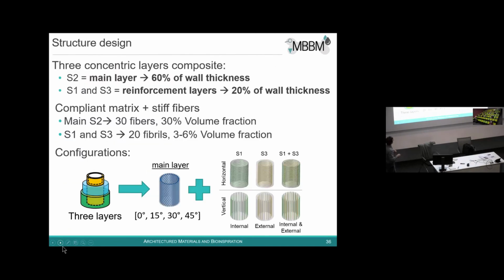So what we did now, we designed, we had to scale this up because of the printer resolution. We cannot print this at the nanometer length scale of cellulose, of course. So we scaled this up to the millimeter length scale. And we printed the system where we have a central layer, which represents 60% of the thickness of these cylinders. And this central layer is then reinforced by smaller layers, S1 and S3, which are about 20% of the total thickness of the system. In terms of fiber volume fraction, the central layer has a volume fraction of 30% of fibers, the rest is a soft matrix. And we have a 3 to 6% volume fraction of reinforcing fibers in these inner and outer layers. And so we combine now different configurations.